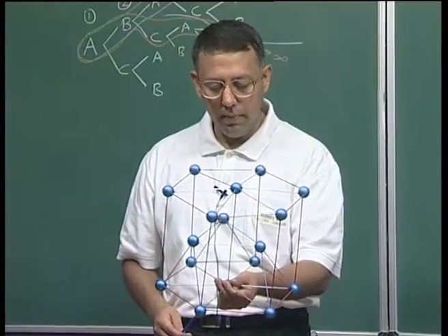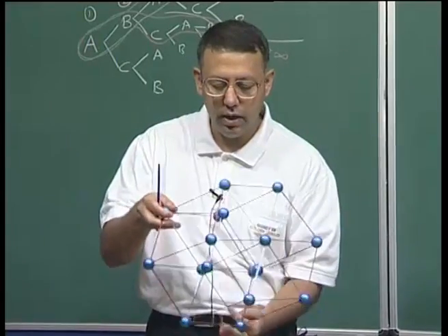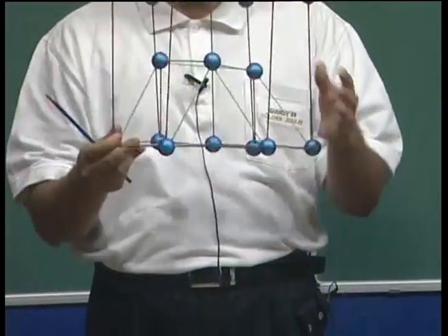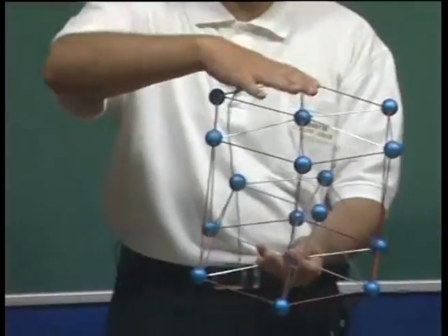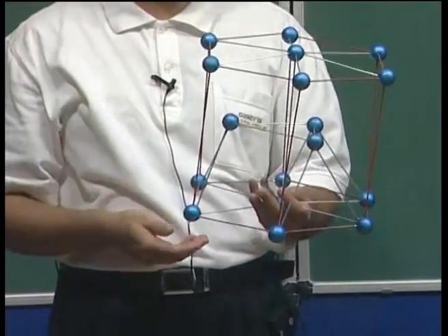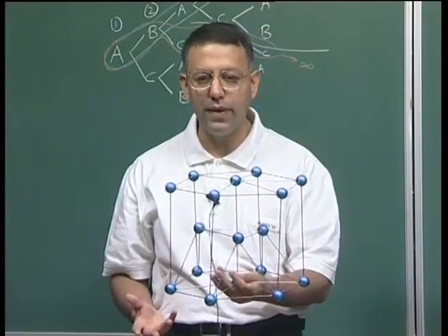Now, as I mentioned, this kind of a structure, let me show from the side, has approximately the ideal C/A ratio. But as I told you, real hexagonal close packed crystals can have a C/A ratio which is different, that means it could be larger or smaller, and that means that the hard sphere model of atoms is no longer valid.